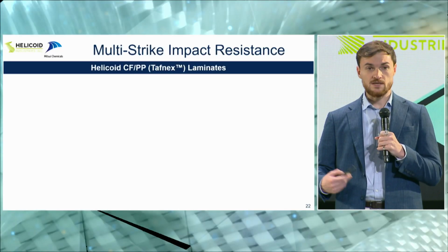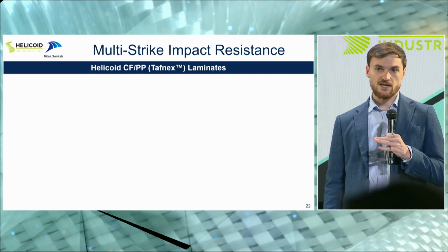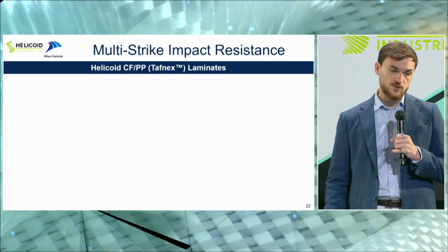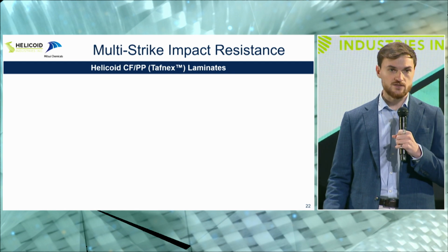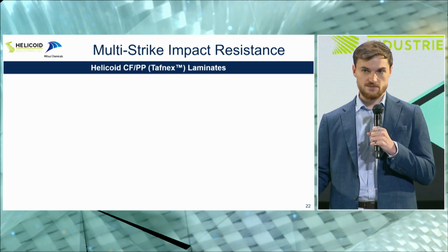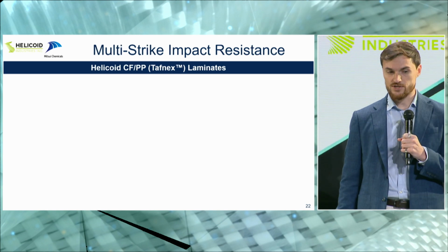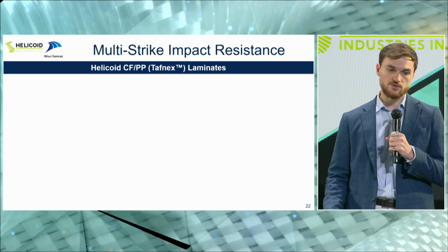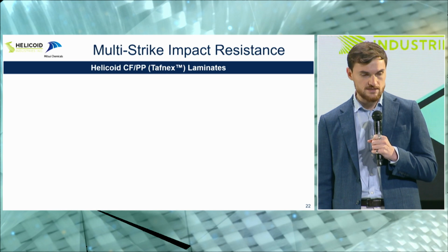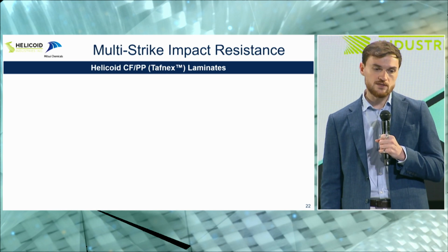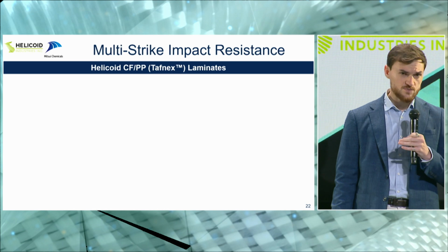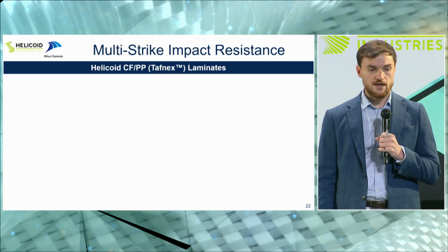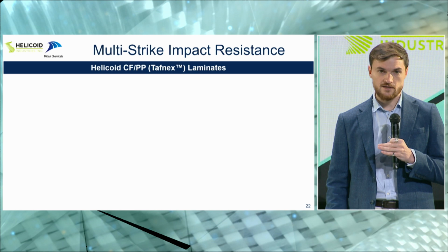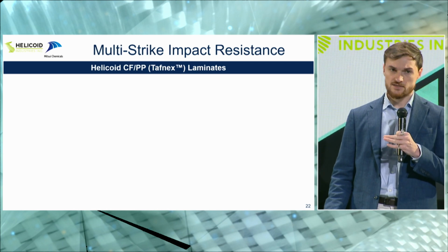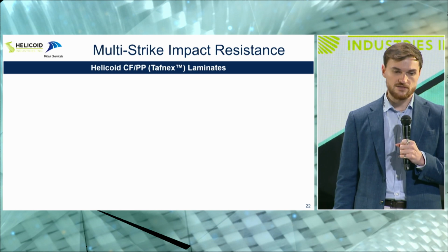The last bit I want to talk to you about is also impact fatigue. So far I showed you examples where we have a single impact, but we have done a lot of testing also to demonstrate durability under out-of-plane loading, such as impact fatigue. In this case, it's a collaboration with Mitsui Chemicals, where we use their carbon fiber polypropylene UD tape, Tafnex, to build a reference cross-ply laminate 0/90 and compare against a helicoid laminate. Again, using same fiber, same resin, same number of plies, same manufacturing technique.